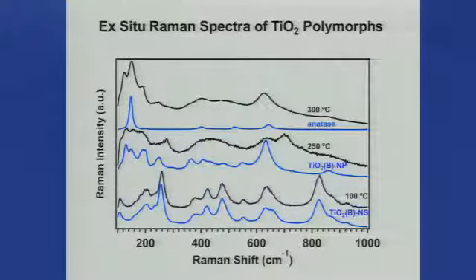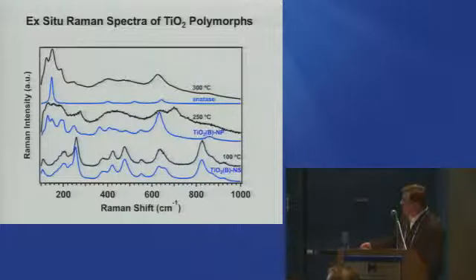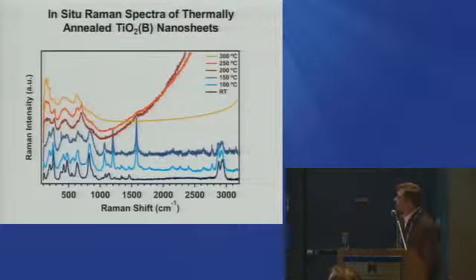We could then heat up the TiO2B nanosheets and watch them convert into nanoparticle morphologies, as evidenced by the change in the frequency of the vibrational modes of the TiO2 and these phonon modes down here. And then we could actually see when anatase starts to nucleate out of this particular TiO2B phase, because anatase has a much more simplified vibrational spectrum.